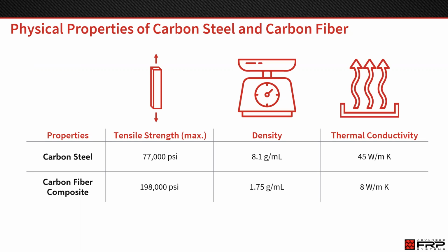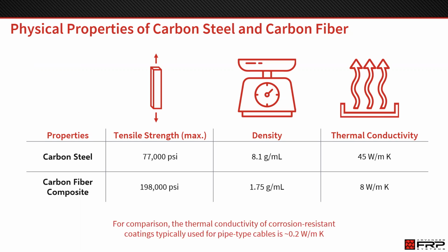Finally, the thermal conductivity. Carbon fiber is a non-metallic, so it is lower in thermal conductivity than a metal like carbon steel. But for reference, a general corrosion-resistant coating is going to be closer to 0.2 watts per meter Kelvin. Carbon fiber is at 8 watts per meter Kelvin and is actually extremely thermally conductive for a non-metallic. This is crucial for underground feeder lines because they rely on the dissipation of heat. So carbon fiber will not inhibit the dissipation of heat through the pipe wall.